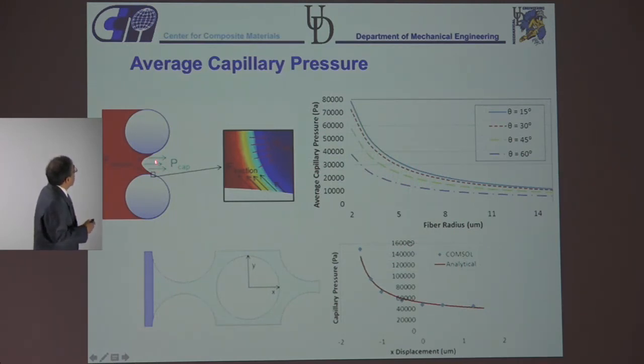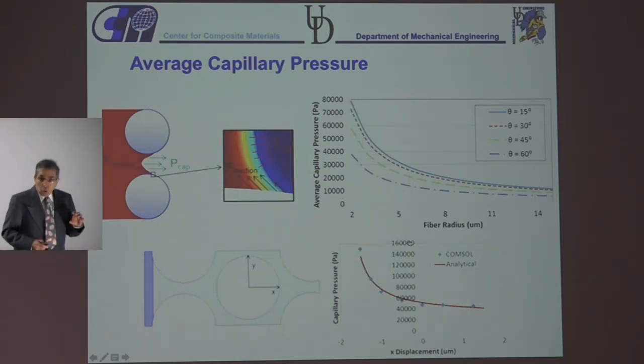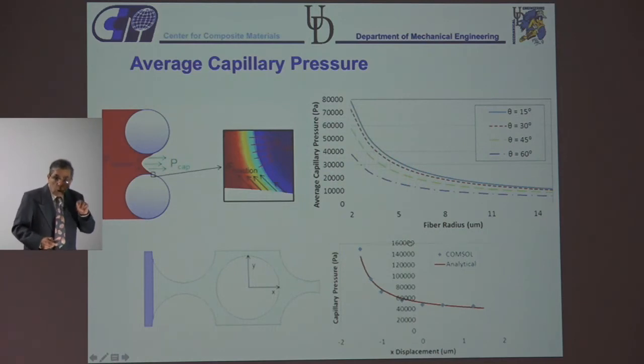And this capillary pressure will depend on the distance between the fibers. So if I take this third fiber, so this is one fiber, this is the second fiber, this is the third fiber. If I move this fiber away a little bit, my capillary pressure can change dramatically. So when you look at a toe, if the fibers are not uniformly arranged, the capillary pressure inside the toe is not the same everywhere, it's different. And that's what we can show from here.